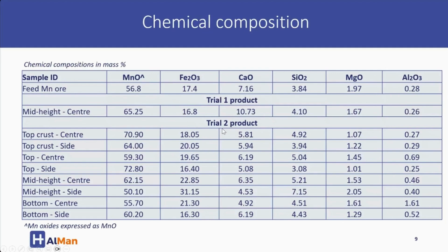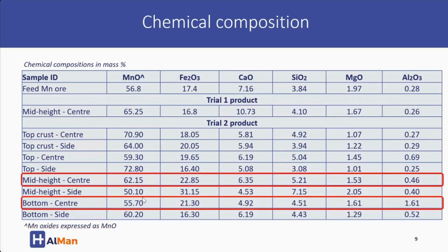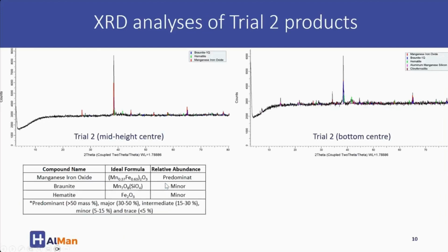In trial 2, we actually managed to get quite a number of samples to show the variations at different heights. Because of the different temperature profiles, you get different kinetics of reduction happening at different heights of your material in the retort. So we took these 2 samples, the mid-center and bottom-center samples, and put them through XRD.